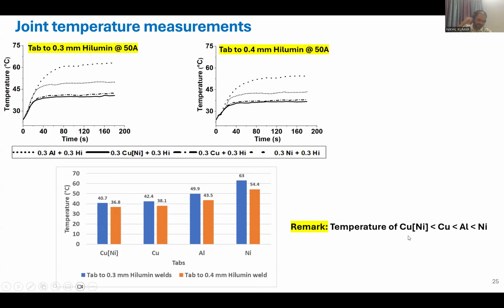So why is this data important? Because if you are going to select some tab, you won't select this one, nickel, because if you're going to use 50 amps current with this nickel tab, then you are going to have a very high temperature rise. Then your cell is not going to survive that 60 degrees C temperature. So you have to select either nickel plated copper or copper. That's why this data is very important. So for 50 amps current, you have to use either nickel plated copper or copper as the material for the tab.